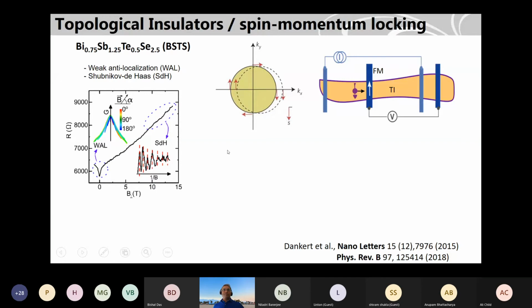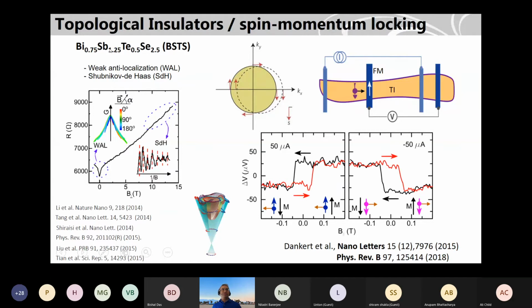So here I will show you some of the results from our lab on BSTS. This is an alloy of different elements, which actually gives more surface conduction than the bulk. And we could see Shubnikov-de Haas oscillations. And what we want to measure here is that we take such a material, a topological insulator, BSTS, and then we have this ferromagnet, and we have this current source.